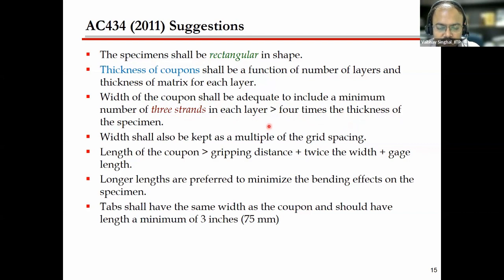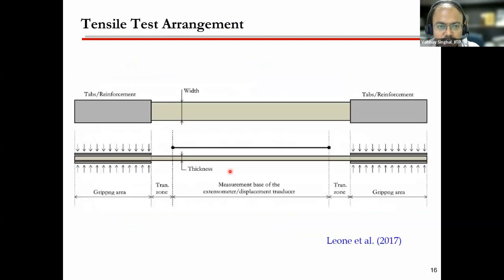thickness of the specimen. The width should be kept as a multiple of a grid spacing, and the coupon length should be the grip distance plus twice the width plus the gauge length. And the longer the specimen, the more preferred, because the bending effect will be smaller. So this is a typical size of a tensile coupon. You can see this is the width, the thickness. The total length will include the gripping area and also the area where you will measure the strain. And then there is some transition zone.